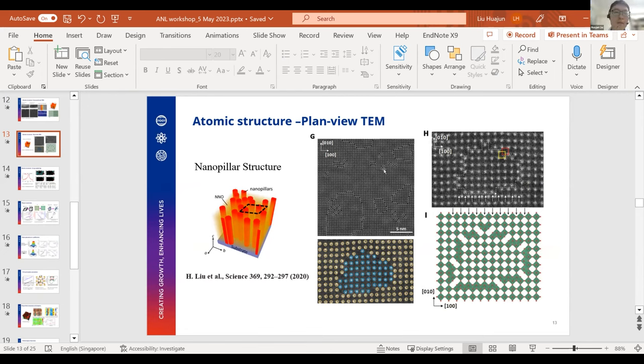So basically, the size of this is about a few nanometers, the scale bar is 5 nanometers. I think the acoustic wavelength is much larger than this, so possibly there's no difference to the acoustic waves. Okay. Yeah, that's what I was understanding. We hope to control this size, but it's quite difficult. I think it's a self-assembled process. Yeah, okay.